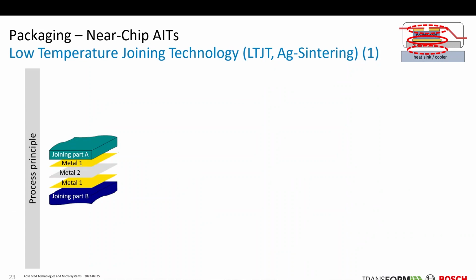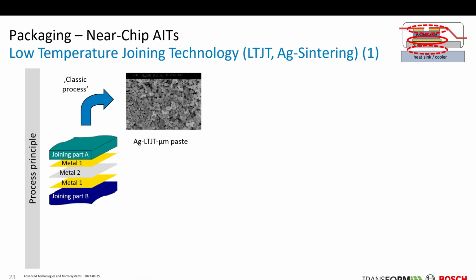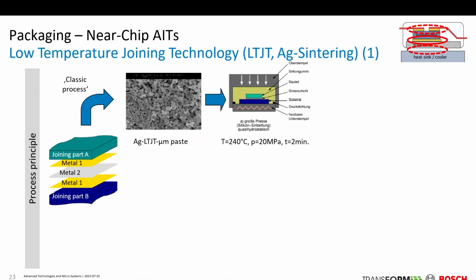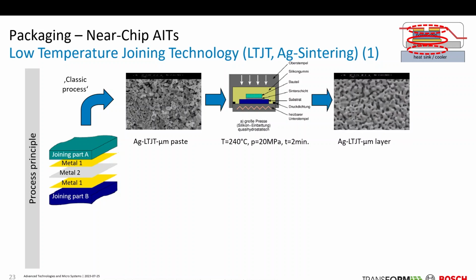More or less well established now for power electronic modules is the so-called sintering technology, silver sintering technology, or some people call it low temperature joining technology, in short LTJT. The buildup of your system is quite the same as shown in the last slide. You need the joining partners A and B. You have this very special metallization situation. But then, in classical silver sintering, we have a paste with silver flakes inside. As well, you need time, temperature and pressure. And then you will receive this silver sintered layer.